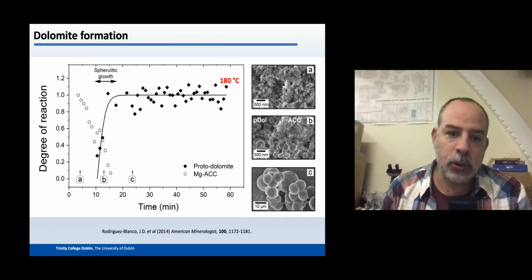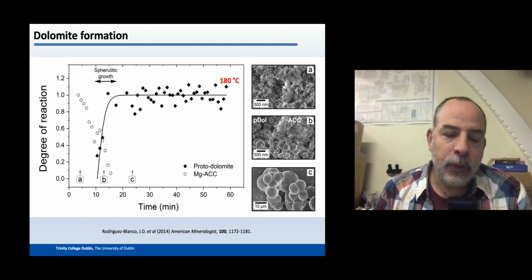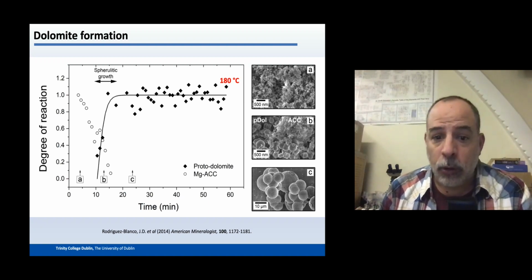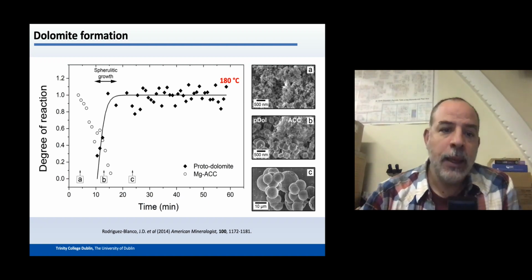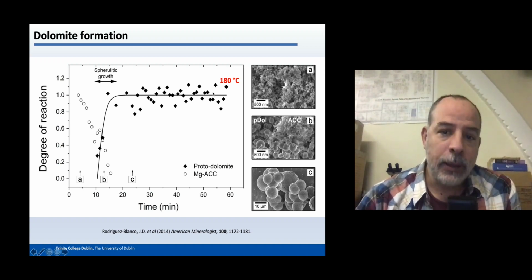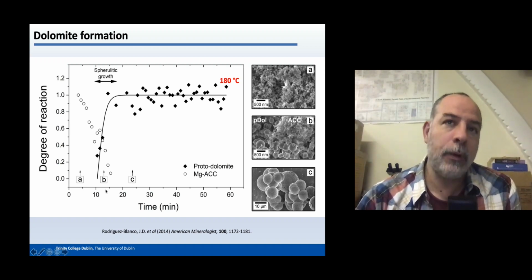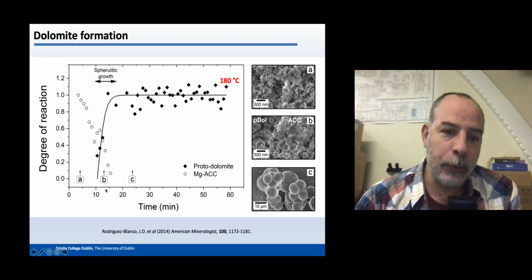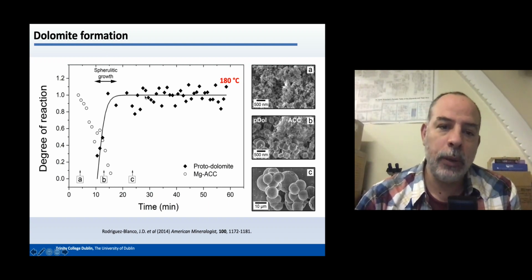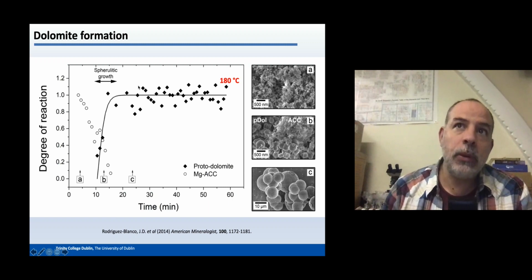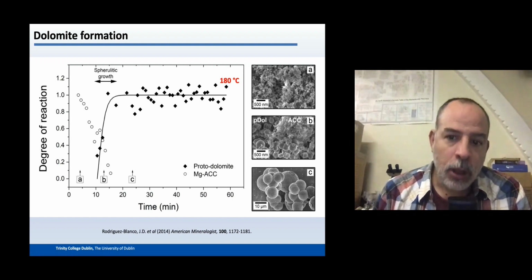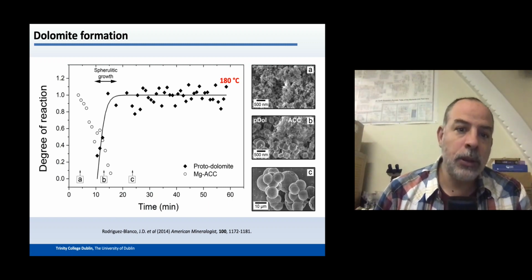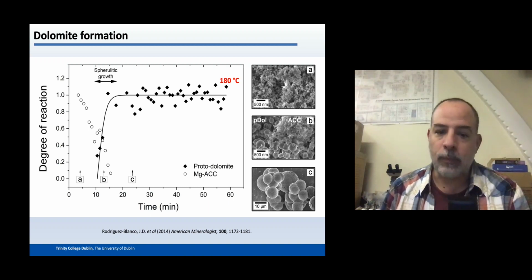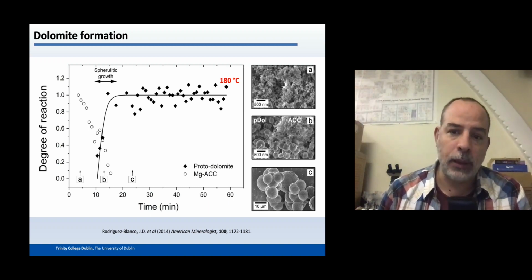We need high temperatures to produce dolomite, and therefore it will not be possible to follow the crystallization of dolomite without synchrotron-based techniques. You see here at 180 degrees C the breakdown of the amorphous phase, which is a magnesium-rich amorphous calcium carbonate, and the very quick growth of dolomite. This growth is essentially completed in less than half an hour. It will be impossible or very difficult to take samples from hydrothermal reactors and to study this at high resolution. We need synchrotron-based techniques to study this.